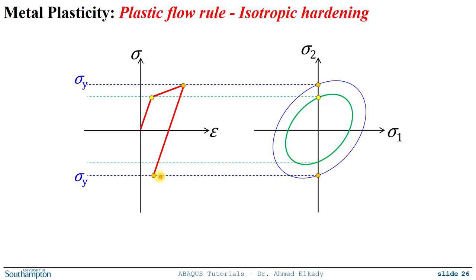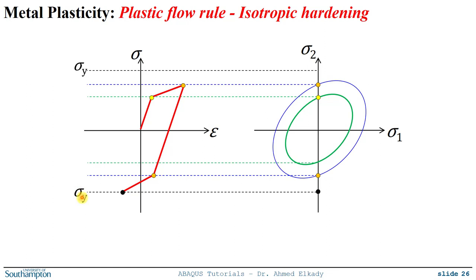And this means right now again that we ended the elastic branch and we're moving into the plastic domain. If you keep loading and you stop at one point, our yield surface shifts, and this will become our new yield point, and then you will have a new elliptical surface. And then if I unload again, I need to go all the way to the top, to this point, the edge of the black or the new elliptical yield surface, and then you get your yield point, and so